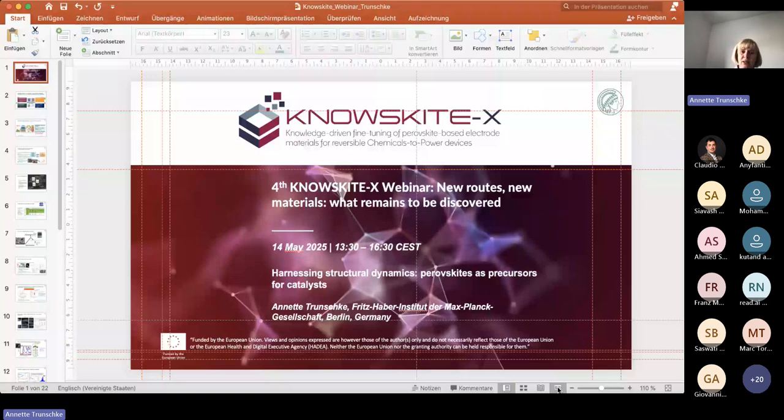And you can study this also with EELS. So if you make, for example, for the samarium manganese oxide, a line scan from the surface to the bulk, you see that at the surface, this is this red spectrum, you have a higher contribution of manganese 2+ compared to manganese 3+.